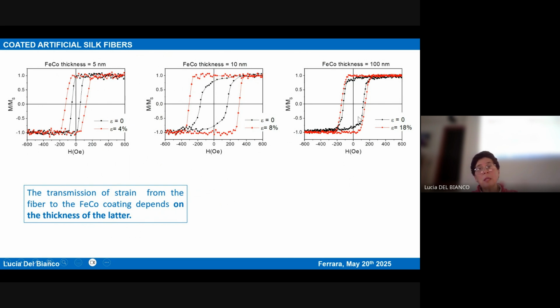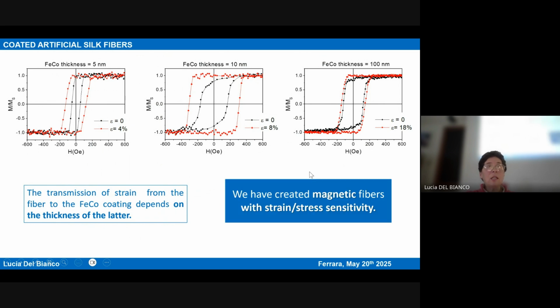But on the other extreme, at 100 nanometer thickness of the iron cobalt, you can increase the strain up to almost 20%, but the change in coercivity is very small. Therefore, the transmission of the strain depends on the thickness of the iron cobalt coating, and this is something that we are still rationalizing. But what is really important is that we have succeeded in creating fibers with a magnetic response, but also with stress-strain sensitivity.